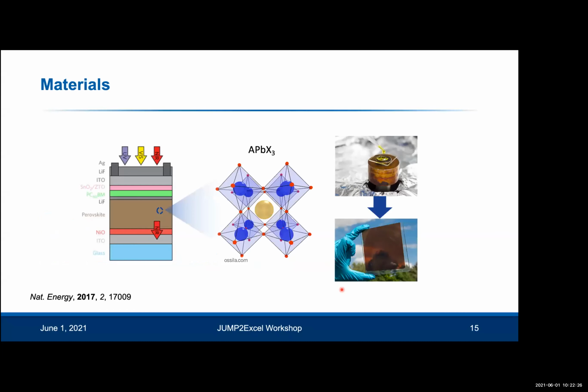So when I talk about perovskites, I'm referring to a family of compounds with this crystal structure that you see here. And in these compounds, we have a B-site cation, in this case lead, which is octahedrally coordinated with halides, for example, iodide or bromide or chloride. For solar cells, usually iodide. And these lead-halide octahedra share corners to form this symmetric, 3D unit cell. And usually the space group would be a cubic space group or a tetragonal space group. And to keep the whole structure together, you have this large A-site cation, for example, methylammonium or a mixture of cesium and formamidinium, which occupy these cuboctahedral vacancies.